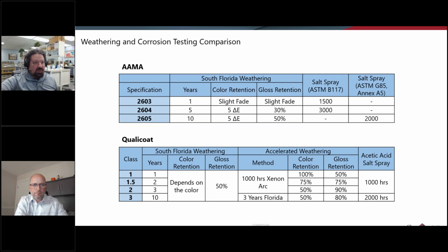There is a salt spray corrosion requirement for these. Since it's on pre-treated, typically chromated aluminum substrate, with powder coatings we really don't have a problem hitting high levels of corrosion resistance on aluminum. If it's on steel, 1,500 or 3,000 hours might be tricky to get with a single coat. But with properly treated aluminum, these are not that difficult.